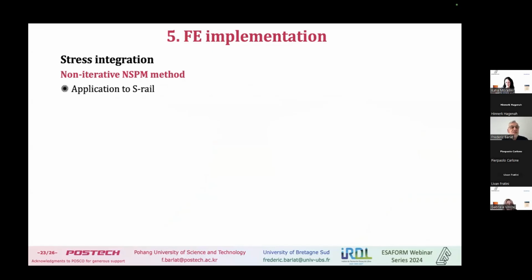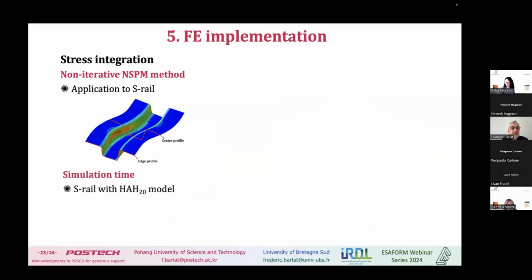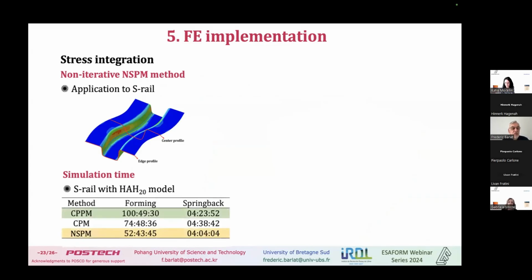So an application of this non-iterative method with S-rail, and I'm not going to present all the detail, but just the simulation time, but the results were almost the same. But for simulation time, we have CPPM, okay, this is the Newton-Raphson method. Here, non-iterative. Okay, you ignore the middle method. But for forming, this non-iterative method takes about half of the time. So 100 hours for CPPM and 52 hours for the non-iterative method on the same computer. For springback it is about the same, but still we save a lot of time for the forming steps.